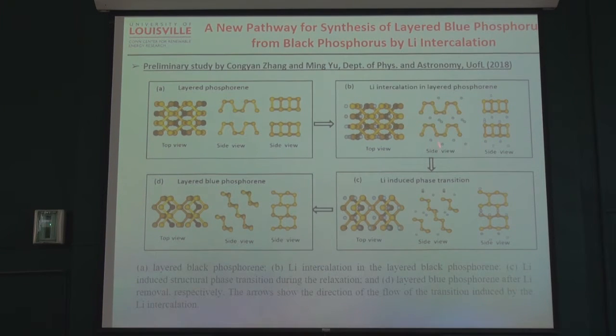Here we show that even without pressure there's a possibility, but we find it's not very easy to do. At this point we need to have high pressure coming in. First intercalate lithium, then apply high pressure. So that can be blue phosphorus.